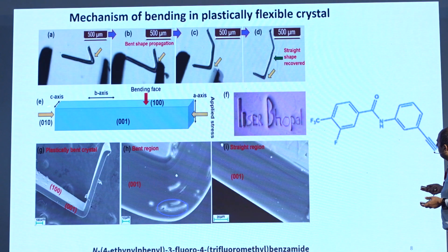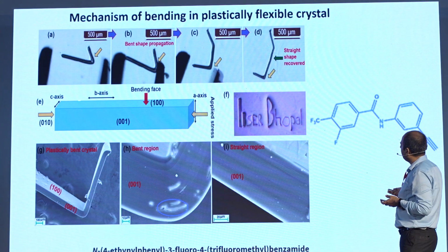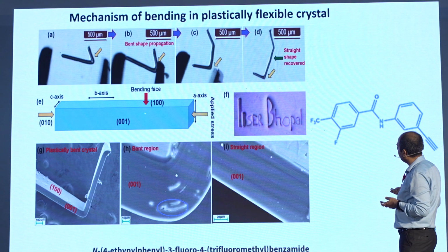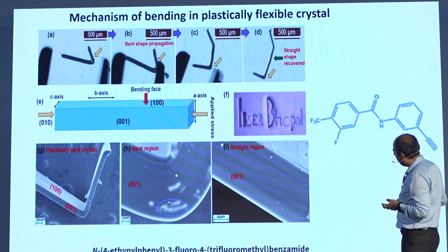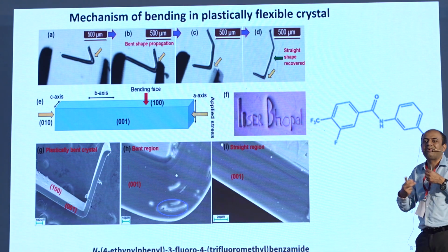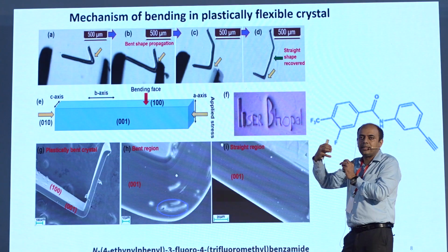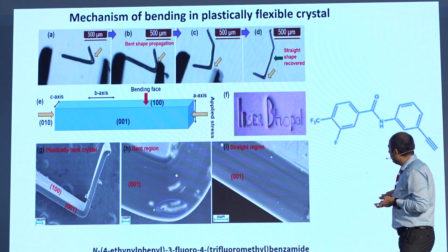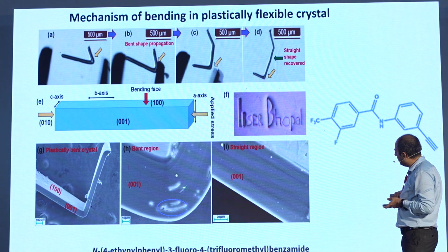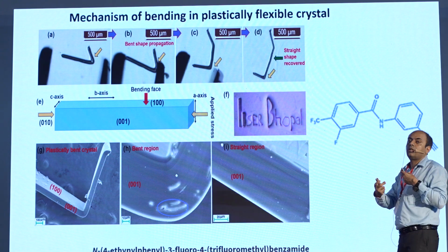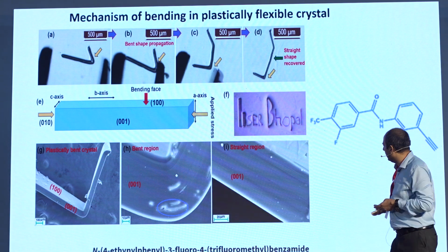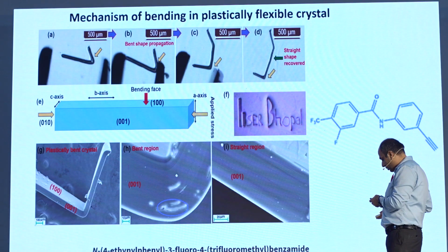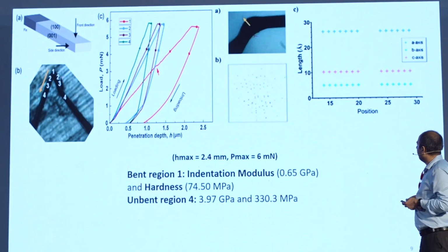And so we take this particular representation where the major face, as you can see, is the bending face. And we also did the TEM imaging to show that at this region, the cross-sectional area where you have the bent region, there is some pile-up of defects. There are defects which are created at the bent region. So we were interested to now see whether at the bent region these defects alter the structure of the material. And in that regard, we planned very advanced experiments.